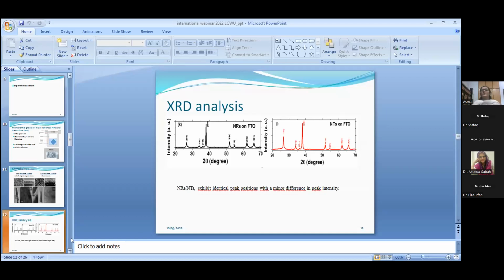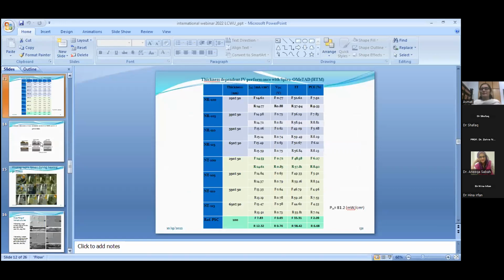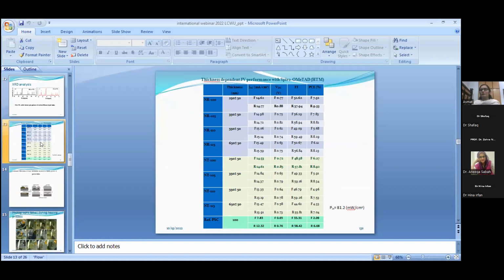Now we have the photovoltaic performance. This is the thickness dependent photovoltaic performance, and this was done with the hole transport material Spiro. As I have earlier mentioned, I use two types of hole transport material. One is Spiro and the second is P3HT. A lot of nanorods and nanotubes were grown, and we use the nanorods from 100 to 115. It means that the nanorods were grown for 100 minutes to 115 minutes.